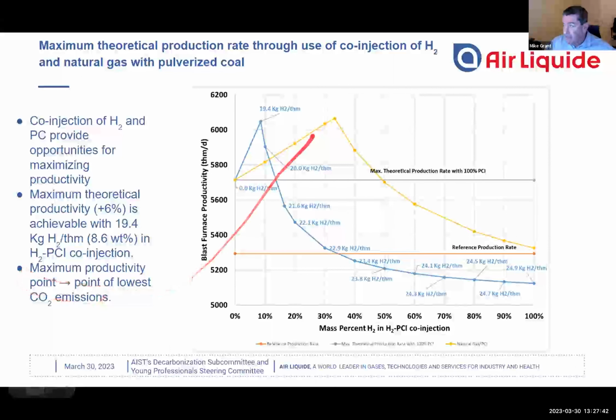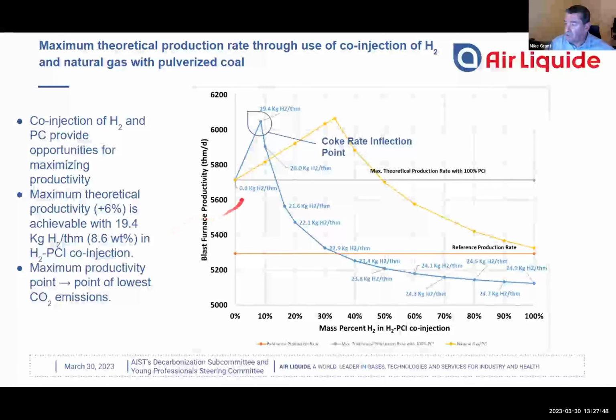This maximum productivity point is also the point of lowest CO2 emissions. So if we can achieve that and get around other practical limitations that the blast furnace might have, we could actually kill two birds with one stone: reduce our CO2 emissions while increasing the productivity of the blast furnace.